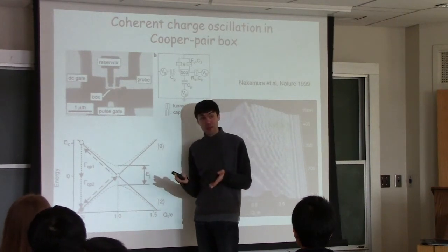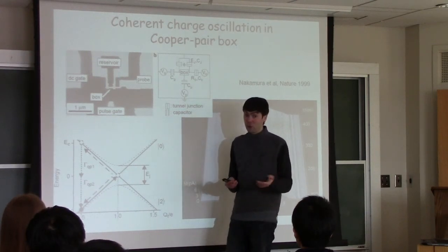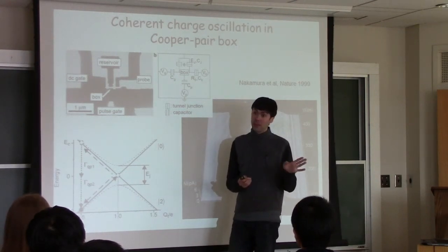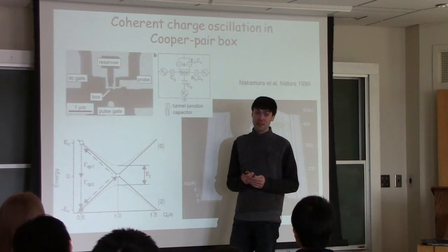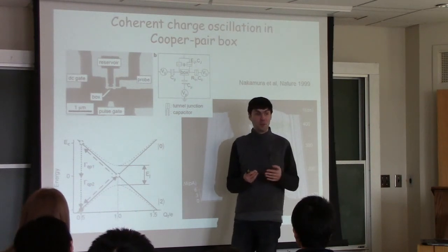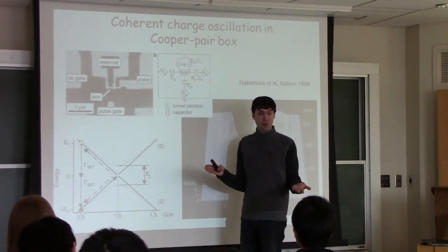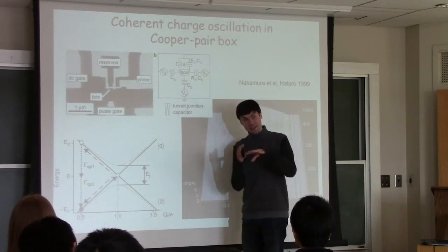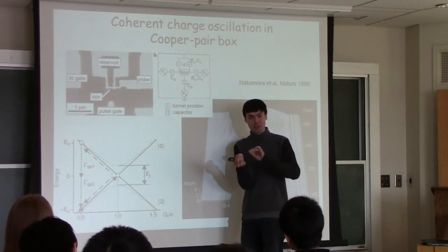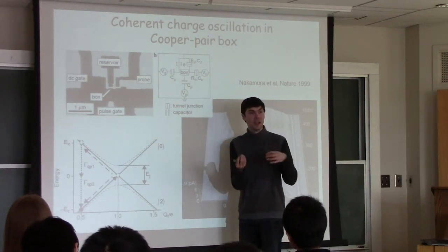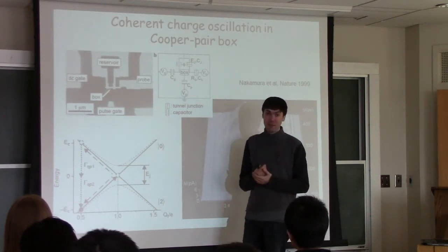And so a flux qubit, for example, which is completely insensitive to charge because the charging energy is small, or a phase qubit, which is nominally insensitive to charge but in practice is actually sensitive, those are better qubits. So for a phase qubit, it's a huge Josephson junction, so the charging energy is very small, but inside the junction itself, you're going to have a bunch of charge imperfections, traps, and charges jumping inside the qubit, inside the junction, and leading to a fluctuating supercurrent. So that limits that qubit.